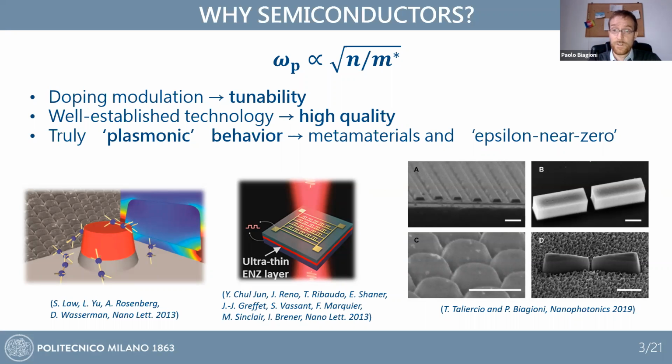that discuss that the proper figure of merit should be something such as the ratio between the plasma frequency and the scattering rate. So higher scattering rates, which indeed occur, you're right, can be quantified. I don't have the numbers with me now, but you can find them in the reference. But they don't destroy the plasmonic behavior so much, because for a given working wavelength, you pay the price of higher losses, but you also take advantage of the higher plasma frequency. And altogether, they balance this effect. So of course, the lower the losses, the better, but it's not true that since you have higher losses with increasing plasma frequency, this will be per se detrimental.